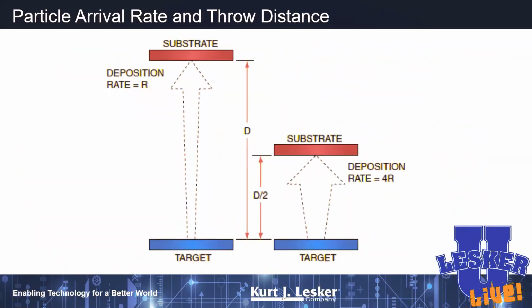Now, if you are interested in deposition rate, one neat trick is to change the throw distance. If we change our throw distance from our substrate to our target by a factor of 2, we're going to increase our deposition rate by a factor of 4. So this is a neat thing you can do. Now, there's some side effects, of course. You may have some issues with film uniformity, film thickness, things like that. But if you're really dialed into deposition rate, one easy trick is to change your throw distance. And if you think about that giant sputter system I showed you earlier for glass coating, the throw distance between those giant cathodes and a piece of glass is about 1 inch.